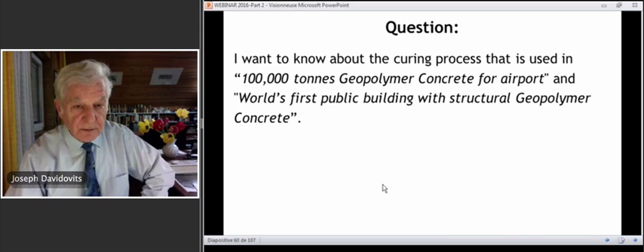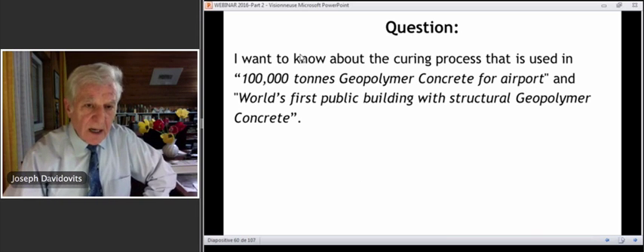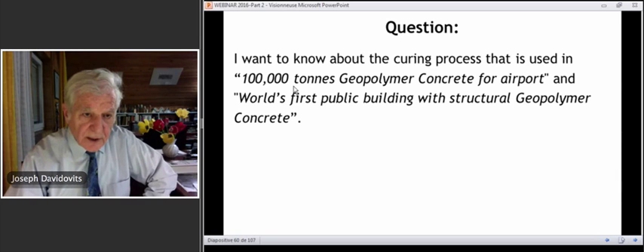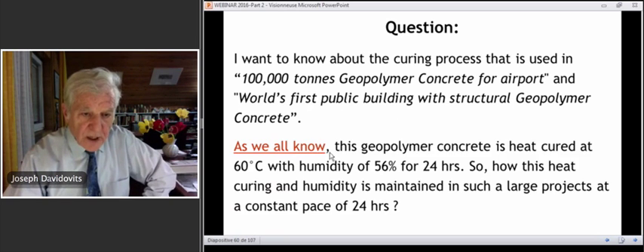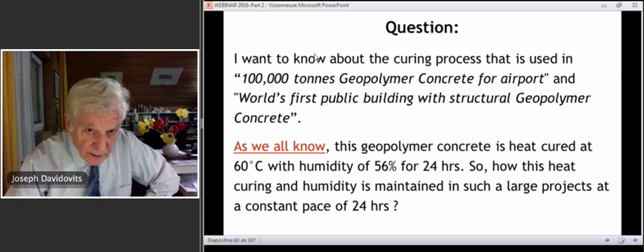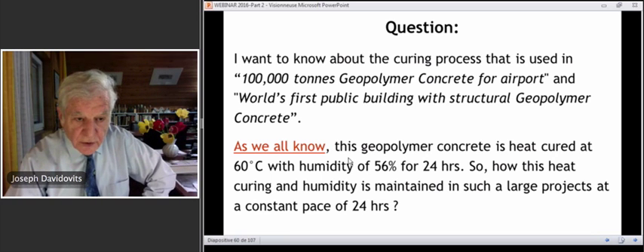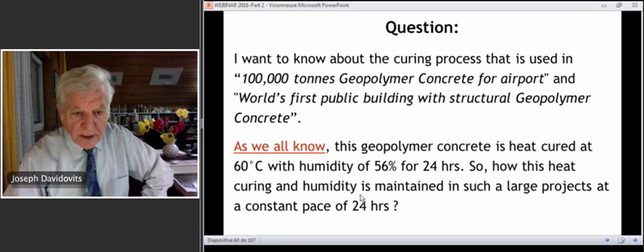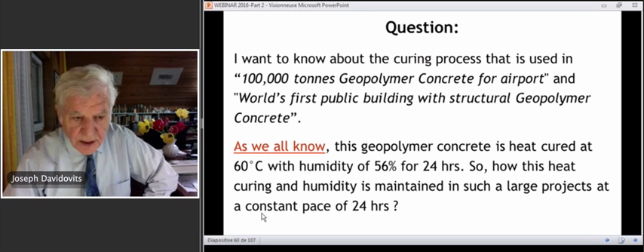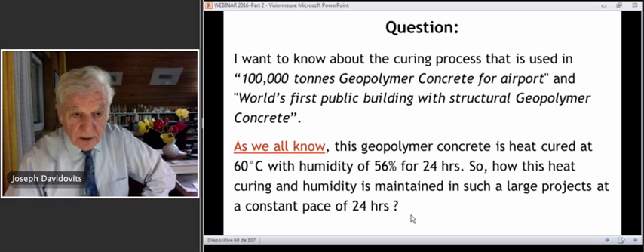And I have another question related to fly ash. I want to know about the curing process that is used in the 100,000 ton geopolymer concrete for the airport and the world's first building with structural geopolymer concrete. As we all know, I repeat, as we all know, this is what I got as a question. This geopolymer concrete is heat cured at 60 degrees C with humidity of 56% for 24 hours. So, how is this heat curing and humidity maintained in such a large project at a constant pace of 24 hours? Wow. As we all know.